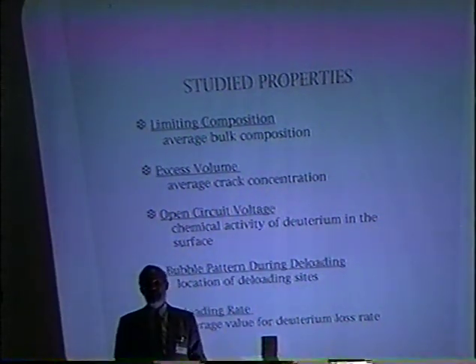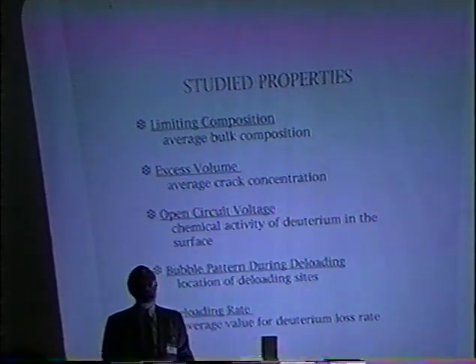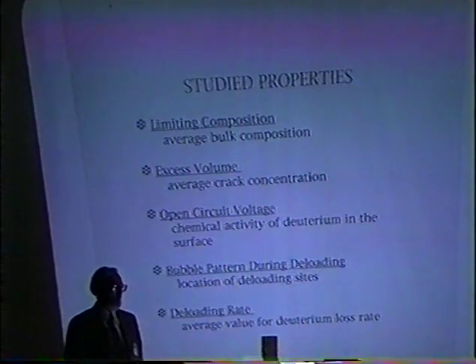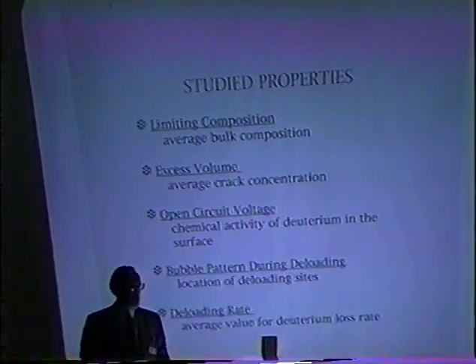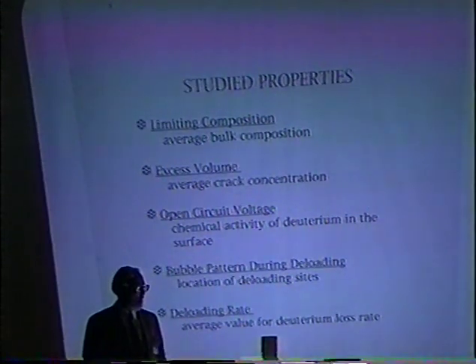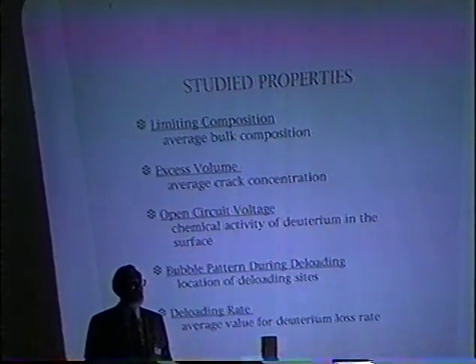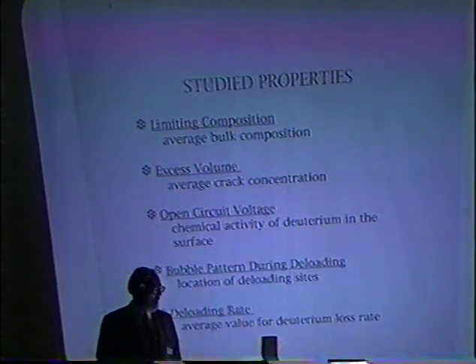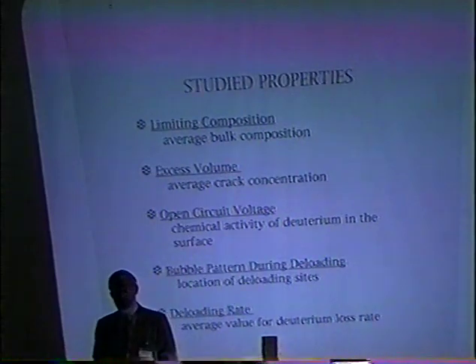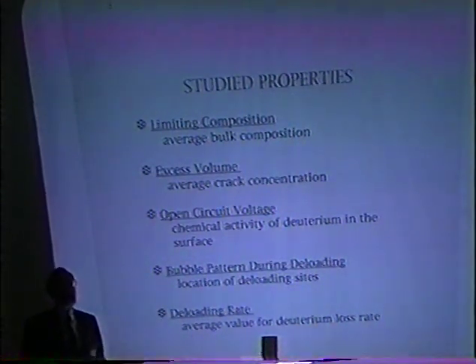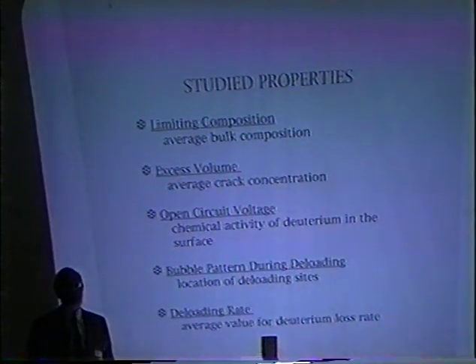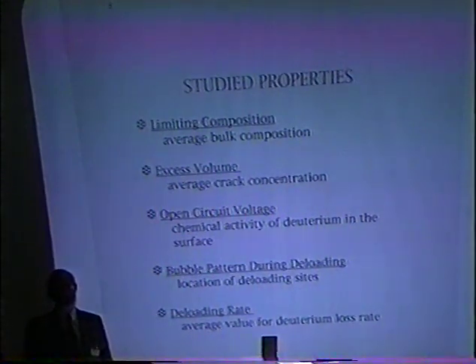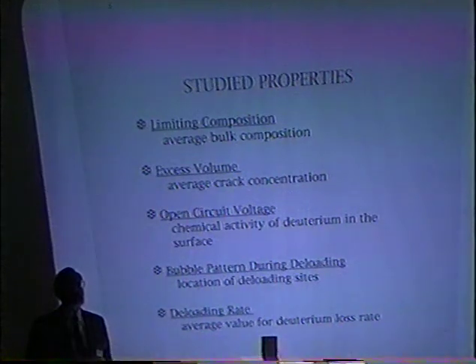Palladium, when it loads with hydrogen or deuterium, forms cracks. These cracks are microscopic, they're invisible even under a microscope, but they do produce a volume expansion of the piece that is over and above what you'd expect on the basis of its loading. Normal palladium has an excess volume between 5 and 6%. At that level of crack concentration, you do not get excess energy. Every once in a while, you'll find a piece of palladium that has between 0 and 2% excess volume. That palladium has a very high probability of producing excess energy.